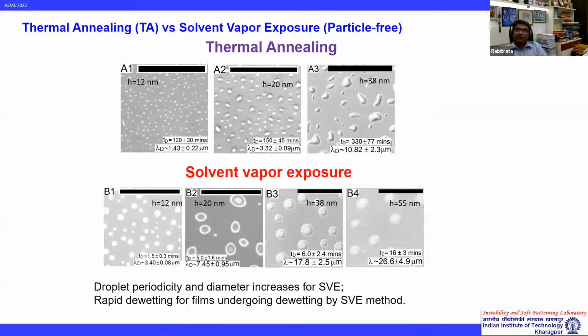So there were traditionally two approaches by which people used to do it. One is by thermal annealing, simply heating the film above its glass transition temperature. The other one was by exposing it to its solvent vapor, where the solvent molecules penetrated, and so there was a reduction in viscosity, or a reduction in the cohesive interaction between the molecules, leading to an effective reduction of the glass transition temperature to below room temperature. However, people in this whole area always used these two approaches almost interchangeably. So nobody looked into whether there is a fundamental difference in the mechanism or the physics of the dewetting system. So we looked into it recently, and we showed that though we say that in both approaches we take the film to a higher temperature, there is actually a significant difference in the way the film undergoes dewetting. So I have the reference a little later.